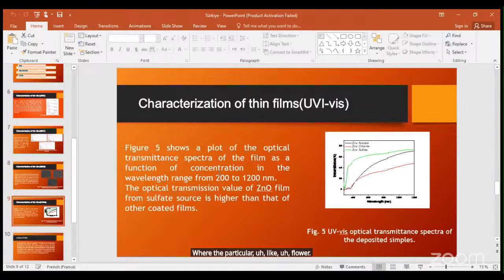Figure 5 shows a plot of the optical transmittance spectra of the films as a function of the concentration, in the wavelength range from 200 to 1200 nanometers. The optical transmission value of the ZnO film from the sulfate source is higher than that of the other coated films.